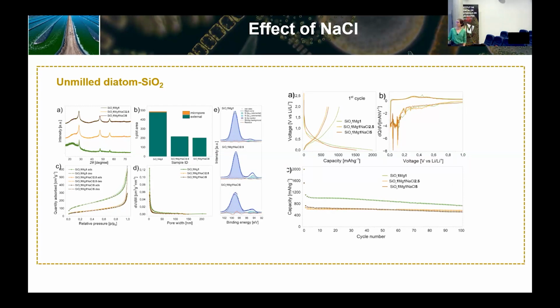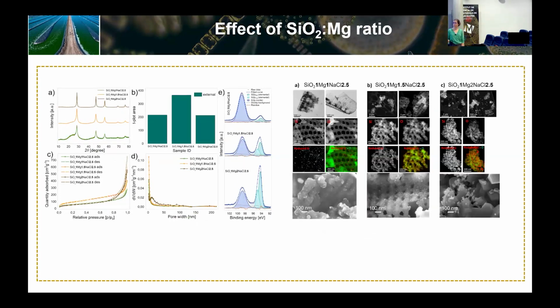You can see the 1:1, that is when we lost the morphology, the capacity was higher, but it's decaying with cycling, and in the other ones, capacity is lower, but more stable. So then we fixed the sodium chloride content and did the reduction for different ratios between silica and magnesium to have SiOx with different oxygen contents. And this is what we got.